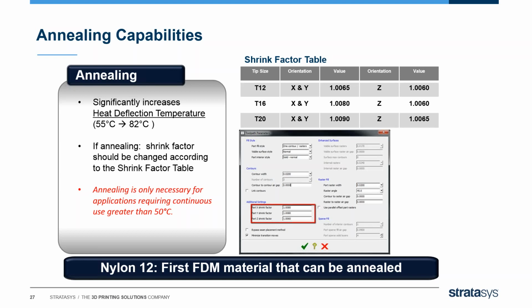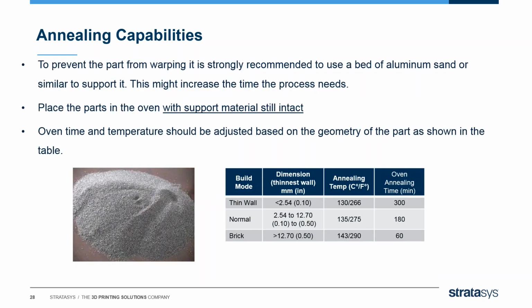Once again, we have recommended parameters for the shrink factor based on the tip size that is used as well, and that's in the table in the top right-hand corner. If you are annealing parts, it is recommended to support them in a bed of aluminum, sand, or similar. Aluminum is a good conductor of heat and keeps the temperature consistent around the part, reducing the likelihood of them warping during this process.